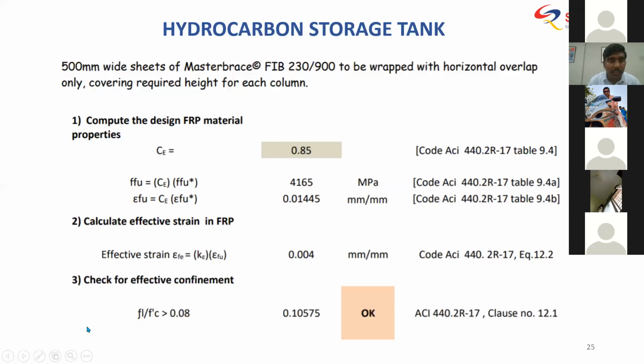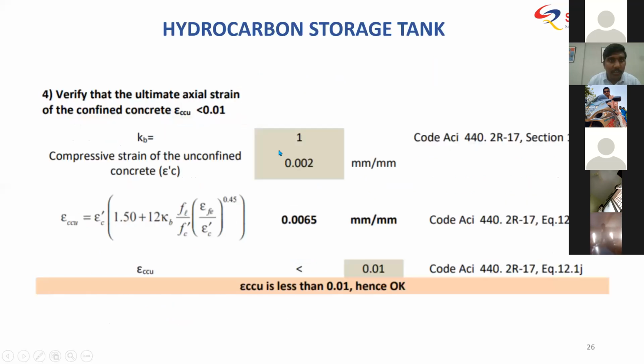Then you have to see whether the confinement provided by the FRP is sufficient or not. So FL is the lateral strength that is provided, and FC is the existing concrete compressive strength. You need this factor to be more than 0.08. And then you have this kappa B, which is a shape factor, which for circular columns is 1. Epsilon ccu is the maximum compressive strain, which has to be limited below 0.01.